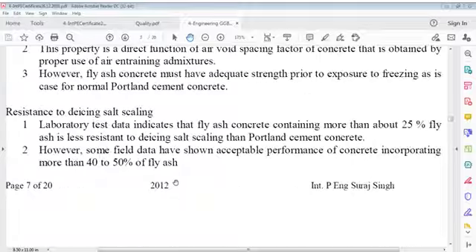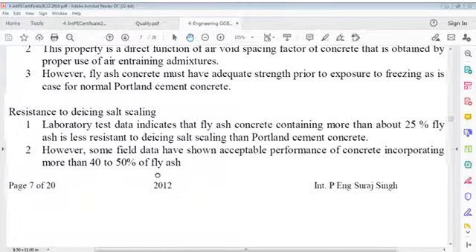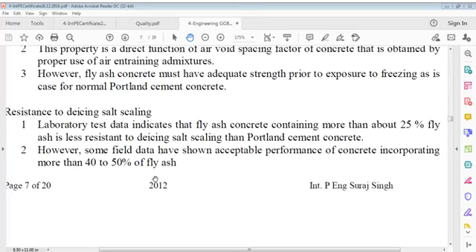Resistance to de-icing salts scaling. Laboratory test data indicates that fly ash concrete containing more than about 25% fly ash is less resistant to de-icing salt scaling than Portland cement concrete. However, some field data have shown acceptable performance of concrete incorporating more than 40 to 50% fly ash.